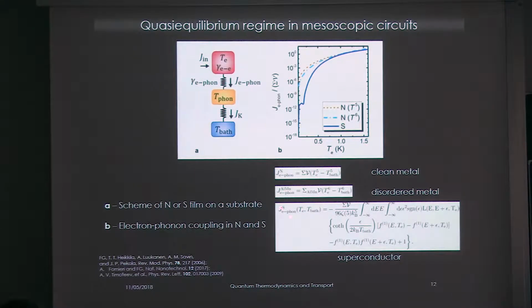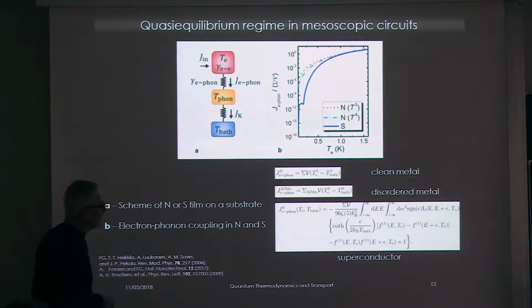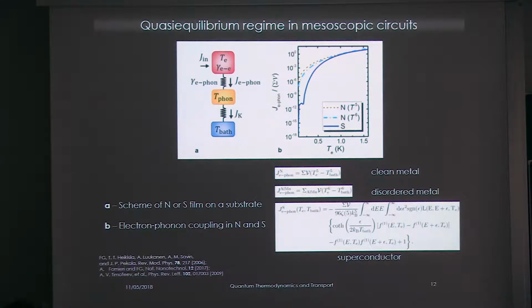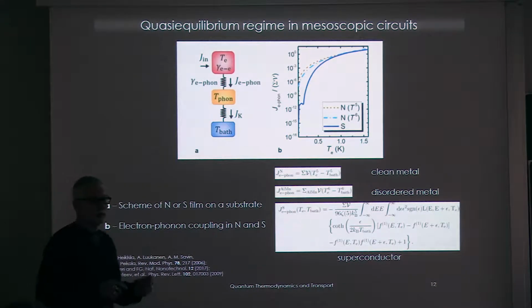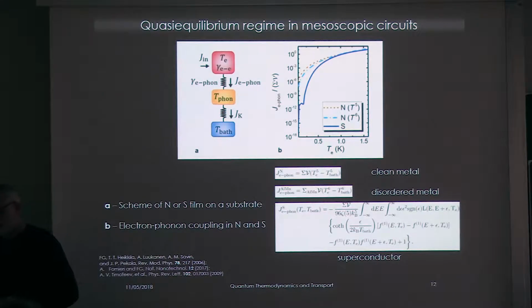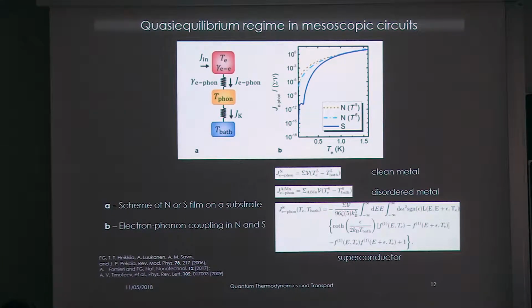And then there is another very important animal, which is a superconductor. In a superconductor, there is a completely different behavior of the electron-phonon interaction, because in this case it is a gapped system. There is a gap in the density of states. There is a condensation that gives rise to the phase transition. And so the electron-phonon coupling can be extremely weak and can be vanishingly small at low temperature. This can be an advantage and a disadvantage, in the sense that the superconductor can be extremely easily overheated or overcooled. This is probably why qubits have problems with superconductors, because it is very difficult to remove heat, and whenever you go to measure them and touch them, you create quasi-particles and you overheat them.